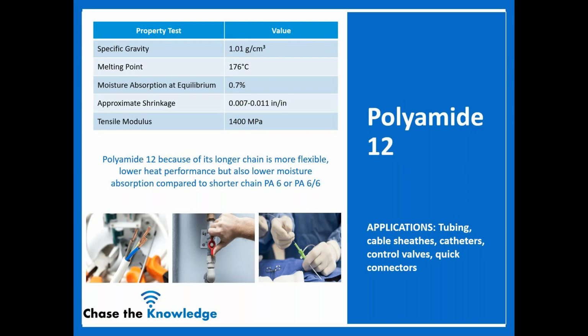And so your tensile modulus will be lower in these grades versus your shorter chain 6 and 6,6, which you'll see as we get through these slides, it'll be a lower value. So tensile modulus on a 12 is about 1400 MPa. And so maybe keep that in mind as we go through the next one.